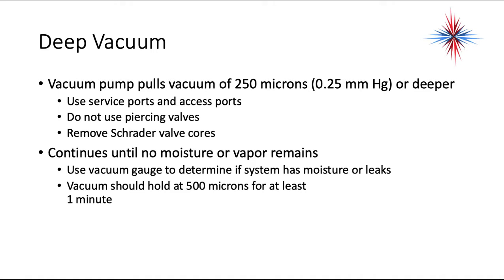Now, while the slide does not say this, one of the things you always want to check is to make sure your hoses are good on your gauge sets. A number of years ago, we ordered a batch of hoses at the school, and there were little pinholes in the hoses on the high side. Not enough that we were seeing refrigerant leaks, but we could never get the systems into a vacuum. We put the hoses under extremely high pressure nitrogen, I think we used 600 psi, and then put them in a trash can of water, and we were able to see the bubbles. So if for some reason you can't pull a proper vacuum, check your refrigeration gauge hoses.